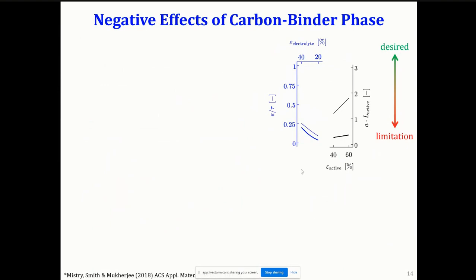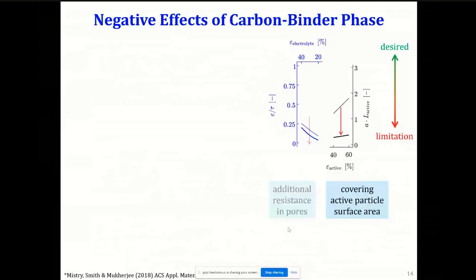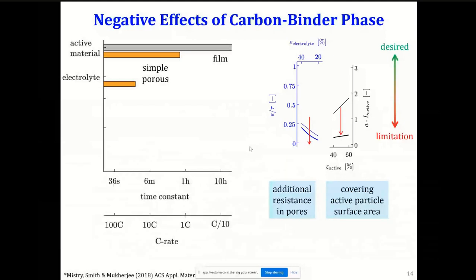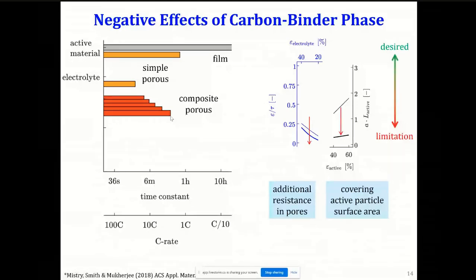Now, if you have this new phase, there's an additional issue, because these phases are now covering the surface of active particles. So you're going to be docked in terms of the active area that is available for reaction. Equivalently, this will create more tortuous pore networks, and so you're going to increase your transport resistance, which will make our life even worse. And if you go back to this time constant plot, this is how things will look. When you have these composite porous electrodes, your time constants for electrolyte transport become even larger. That means you're going to run into these limitations faster and faster.